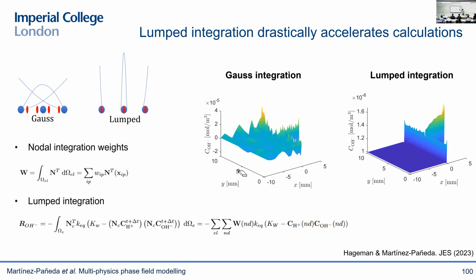And this is just one example. When we were using COMSOL or any other commercial package, due to numerical oscillations, we had a lot of convergence issues because these PDEs can become very stiff because of the high reaction rates. So it would take us a week in the supercomputer to simulate corrosion processes going over 10 minutes. And 10 minutes is not the time scale that we're interested in. But when we use lumped integration, we could stabilize this much, much better. You can see here, this is the result of one iteration. You can see that this is very close to actually the real solution.